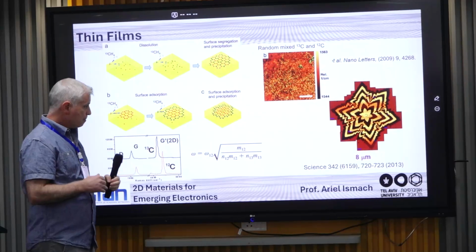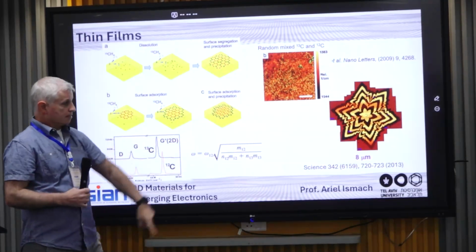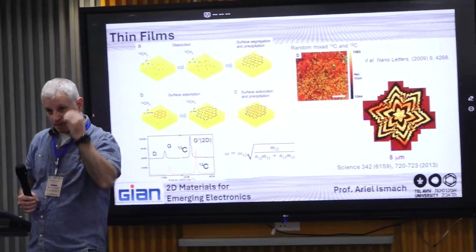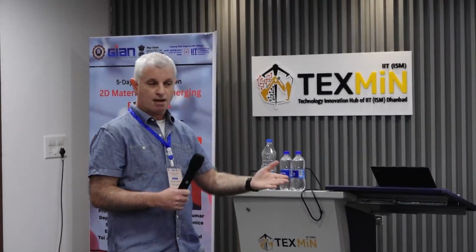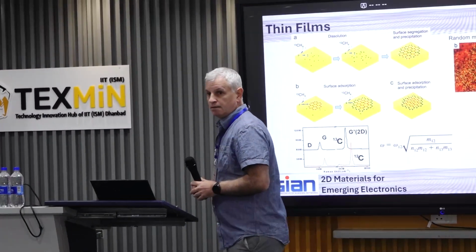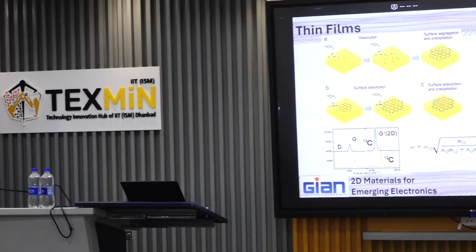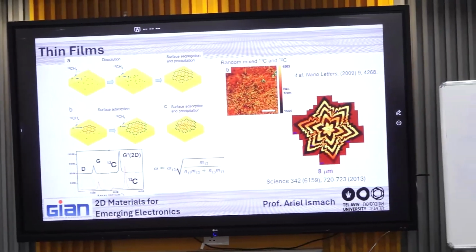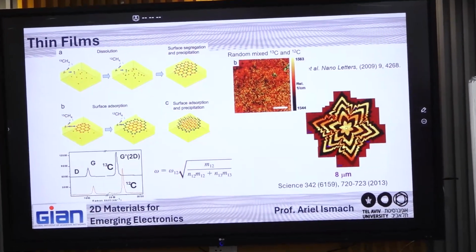But on copper, because it's surface mediated, you can see that, and this is the proof that the growth mechanism on copper is completely different from the growth mechanism on nickel. Copper is surface mediated, while nickel is diffusion and segregation. So does it always form this curved shape on copper? Do you always take that shape?